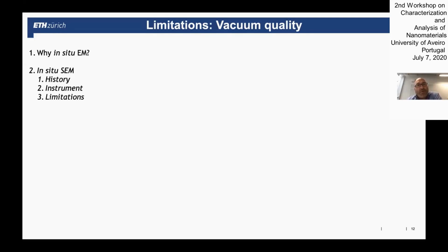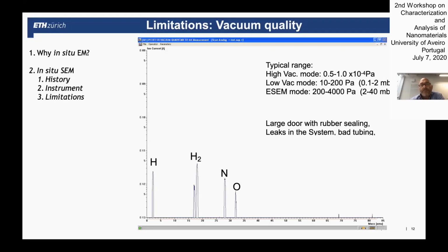So the vacuum is rubber sealed. And whenever you have rubber components, that is not good for vacuum, and you cannot bake out the machine. So whatever kind of experiment you do, if you need a really, really good base pressure, an oxygen-free environment, then you have your limitations with a scanning electron microscope. So we have attached a mass spectrometer and we measured the composition of the gas. When you pump down to vacuum level, you still see that there is hydrogen, basically water, nitrogen and oxygen inside the chamber. This is a limitation. For many experiments, I would really love to have a UHV level base pressure. And from there on, I could then introduce my gases and study something under very well defined conditions.